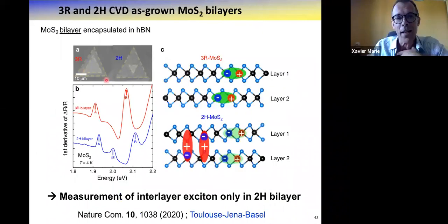And here is an optical contrast, just an optical microscopy image of a CVD grown sample. You recognize the triangles. In some bilayers, you have the 2H stacking, and you clearly see the two triangles with a 180 degree rotation. Whereas for 3R stacking, you have parallel triangles, and you can check the stacking and the symmetry. We have done second harmonic generation to check that indeed we have a 3R stacking, because we have broken inversion symmetry in 3R in contrast to 2H. And here is a result of the optical spectroscopy experiment. First derivative of the reflectivity, differential reflectivity.